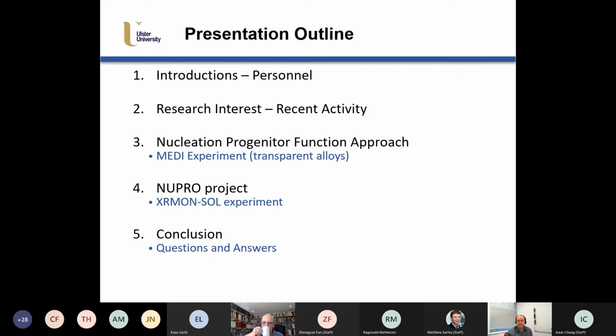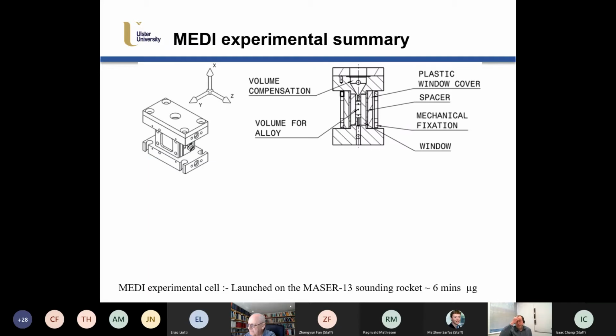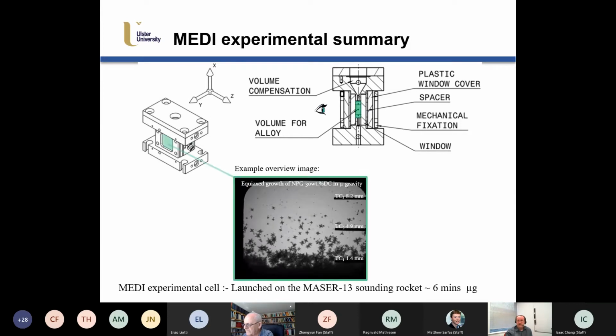Okay, so back to our outline. A very important point to move on to here is to express this nucleation progenitor function approach. The MEDI experiment was flown on the Maser 13 sounding rocket, and it achieved around 6 minutes of microgravity. Within this assembly, you have a little pocket of the sample, heated top and bottom. It has 3 thermocouples inside, and you're able to observe through this window, which is backlit, so you can see all of the equiaxed crystals. One of the nice things about the neopentyl glycol-d-camphor alloy is that it's quite a good equiaxed former. So at low temperature gradients, it was able to perform equiaxed growth.